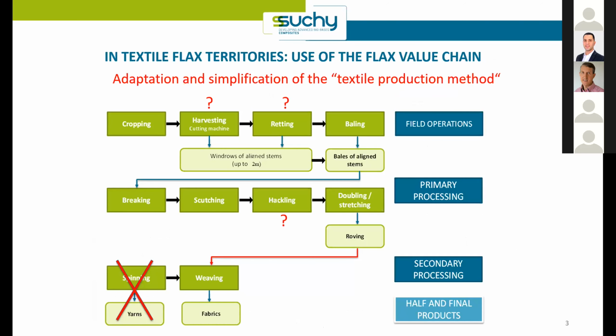It's a lot of boxes in here, but the idea is to adapt, maybe simplify a little bit, the textile production method. There are a lot of steps which are quite similar to those of textile flax, but with a few differences, especially for the harvesting, with different machines required because the plant is not the same. But except for this harvesting machinery, we try to use as much as possible the textile flax machines for the field operation, the primary processing, as well as the secondary processing, and try to go directly from the roving to the fabric without using the classical wet spinning approach, for example.